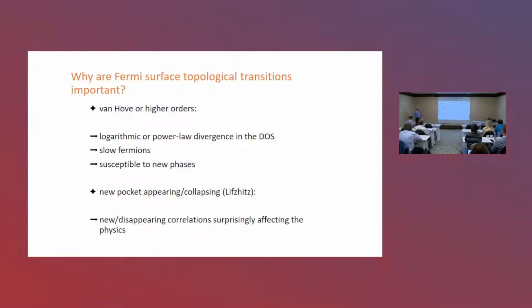We have the two classical types of Fermi surface topological transitions described by Lifshitz. One is the neck formation or collapsing, which is the usual, the ordinary Van Hove. The other is a new pocket appearing or disappearing. And in this case, it has also been shown that there are surprisingly new effects, even through a new pocket that appears or disappears.